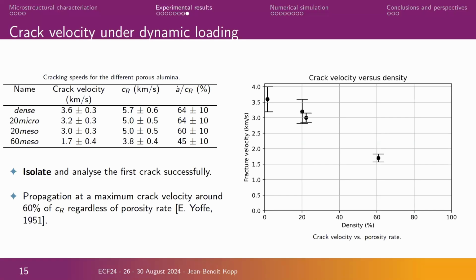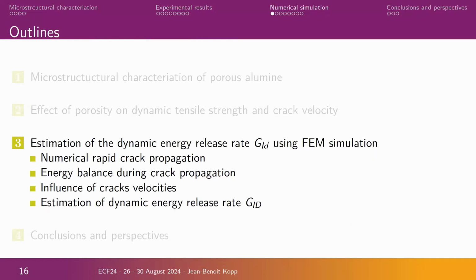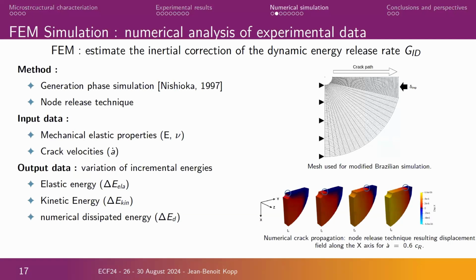So that's interesting because we have a test in mode 1 at the maximum velocity, so we can measure and estimate the fracture energy. So to do that, if I have more time to explain a little bit, we use a classical simulation with finite element method. This kind of methodology is well known. We use a generation phase simulation. So the input of the model is finally the crack path history, the crack velocity. And by doing that, it is possible to make a global energy balance to estimate the fracture energy and finally the energy consumed by the crack during the dynamic regime.